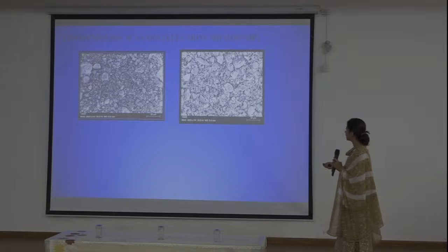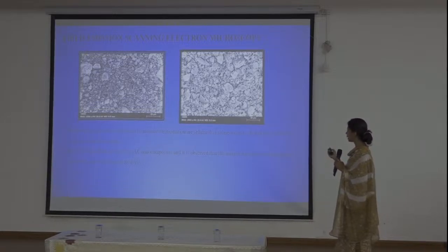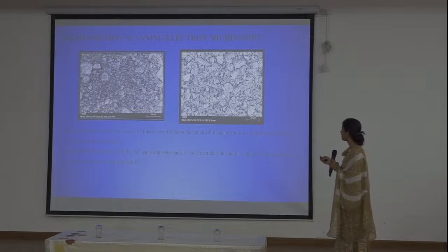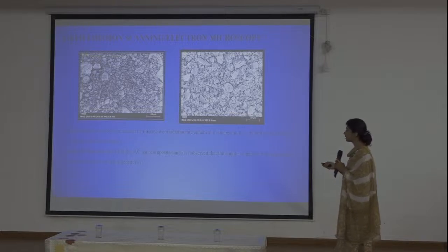This is the FESEM image. The first one shows pure molybdenum disulfide prepared by the microwave method, appearing as small spheres. The second is for the composite, where smaller spheres are homogeneously spread over the spherical shaped activated carbon.